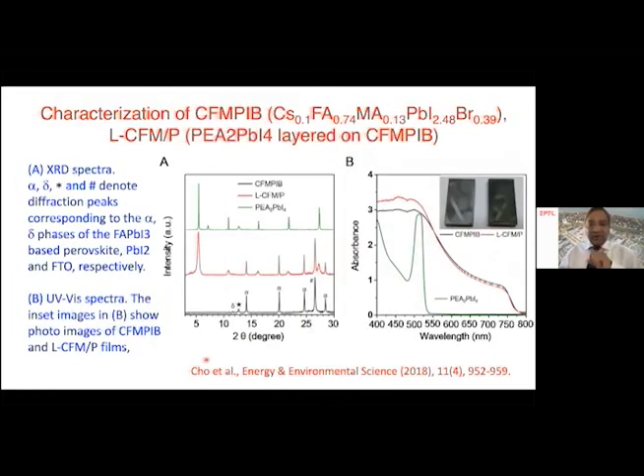So now look at the two-dimensional perovskite spectral properties first. Phenyl ethyl ammonium, taken twice, lead I4. This is the two-dimensional perovskite composition. The absorption spectra, as I've shown before, absorbs up to only 500 nanometers. The maximum is around 500 nanometers. It's a blue absorbing material, the two-dimensional perovskite.